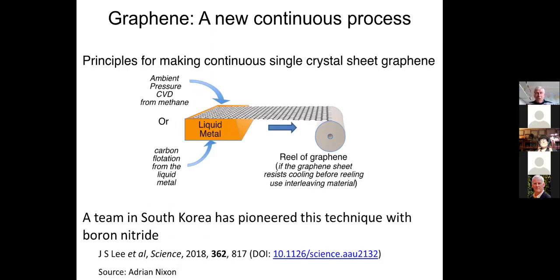So Adrian proposes the principle for making continuous single crystal graphene sheets using liquid metal as a substrate, instead of the existing method, which is doing it on copper film. If you use liquid metal, then it should be much easier to pull the completed graphene off the surface of the metal without doing it any damage. That technique's been pioneered in South Korea with boron nitride. So that looks very, very hopeful, and we're very excited about that work.